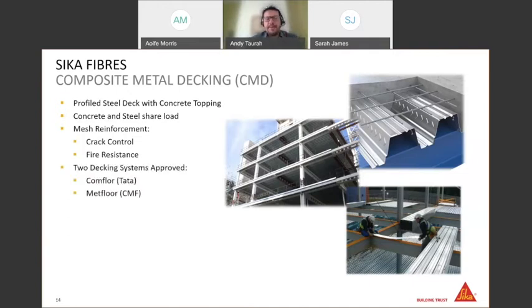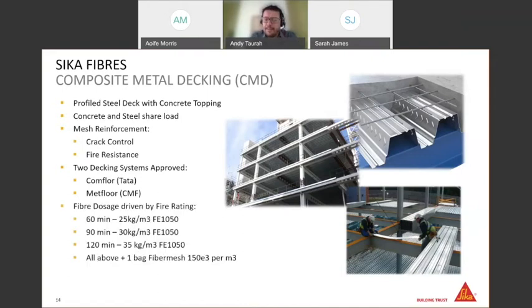So back in the day, Propex conducted fire testing with 2 decking manufacturers in the UK, one being Taurah, the other being CMF. So Propex paid for full-scale testing on these. They constructed full-scale composite metal decks, basically cast them in concrete with steel fibers within the concrete, and then the fire tests were conducted. What that generated for Taurah and for CMF was then the fire rating, which drove the ultimate fiber dosage. And examples there for an hour fire rating, the fiber dosage 25 kilos, goes up to 2 hours and 35 kilos there.